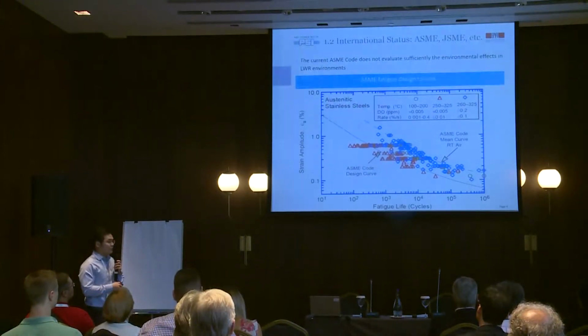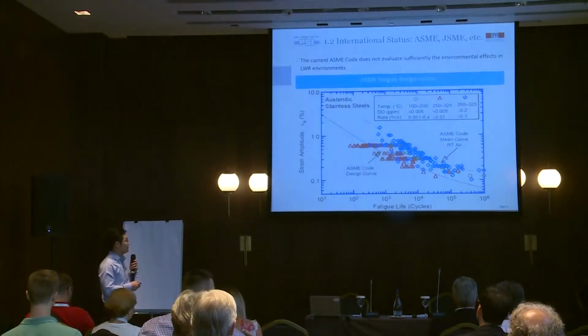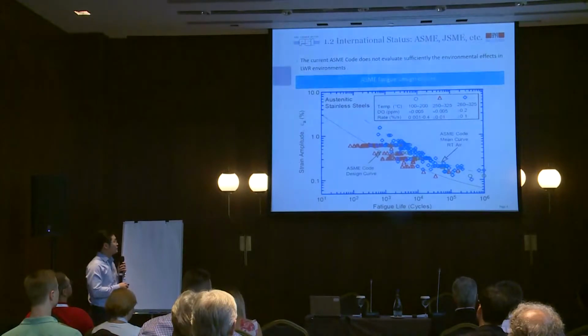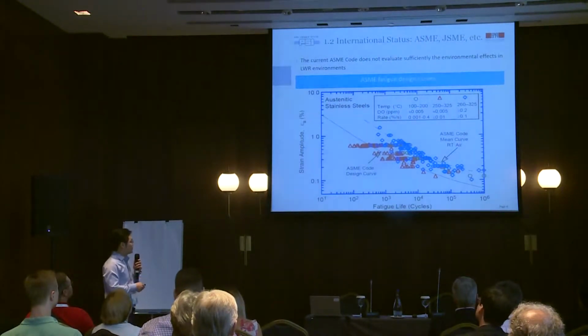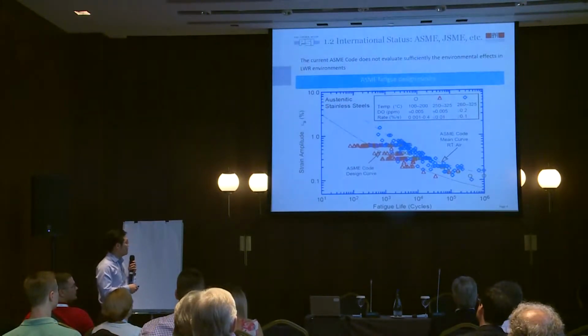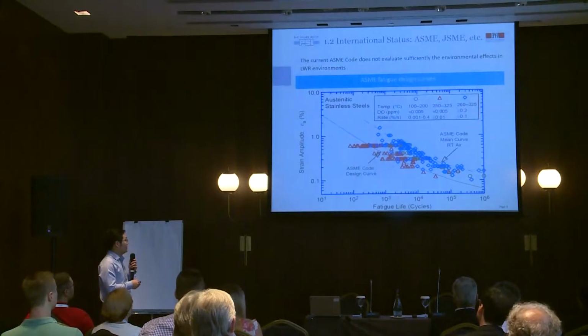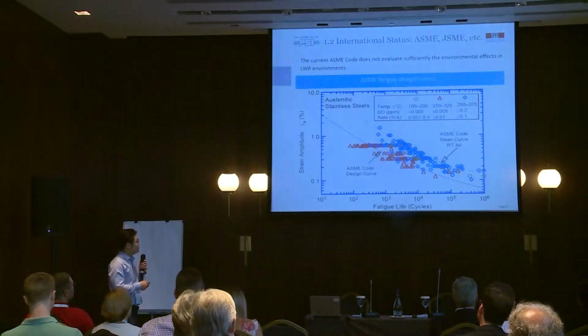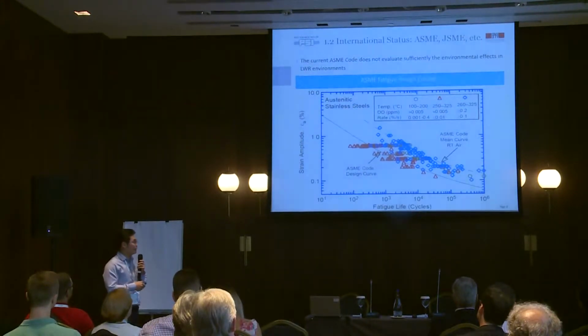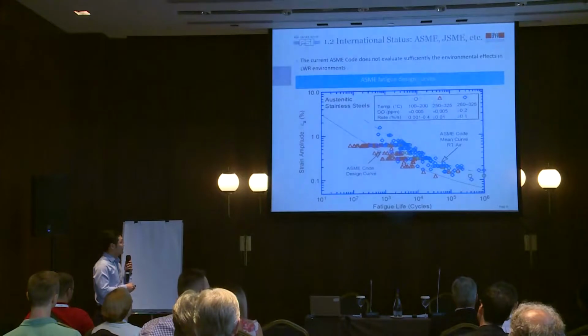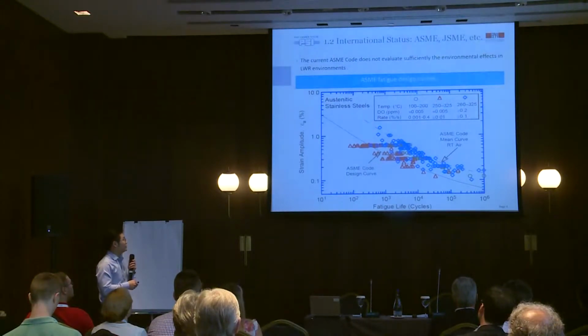The ASME design curve is the most commonly applied method to evaluate the fatigue life of austenitic stainless steel. A correction factor between the design curve and the mean curve has been introduced to provide conservatism in the fatigue design. However, in this diagram, we can see some red triangles drop on the left side of the design curve. That means the ASME design curve is not conservative enough to evaluate the fatigue life of austenitic steel working in an environment where the temperature, strain rate and strain amplitude meet the thresholds concomitantly.